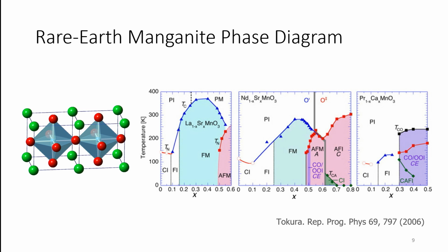So what I'm showing here are what are called phase diagrams. People many years ago created bulk forms of these materials where, in this particular case, at the green side here, you can alloy lanthanum, which has a 3+ charge, with strontium, which is divalent. And by changing how much lanthanum and strontium you put at these sites in the lattice, you can have a very wide range of physical properties.